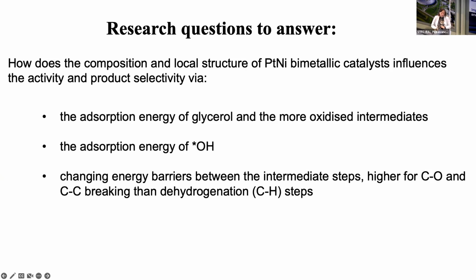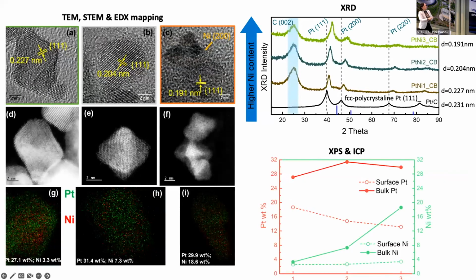So then we characterized these materials. And so you have on top some XRD, which simply shows that we have platinum 111 polycrystalline face-centered cubic phase, and the d-spacing decreases with increasing the amount of nickel as expected, which means that platinum and nickel are indeed alloyed. XPS shows that you have indeed less platinum and more nickel on the surface as you increase the amount of nickel. And probably you can't see these fancy TEMs here, but you could see that you have an almost 1-to-1 platinum to nickel in this platinum nickel 2 material.